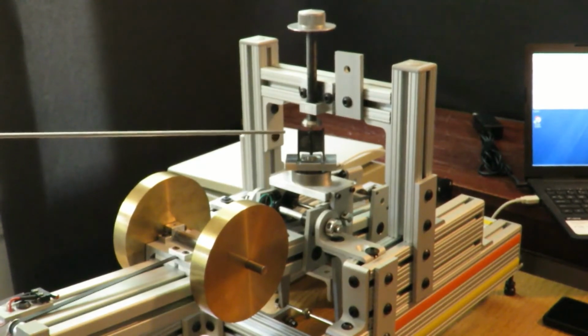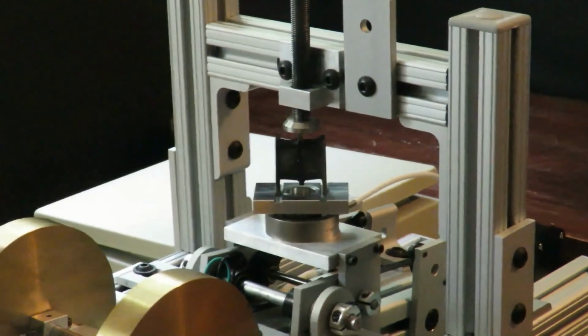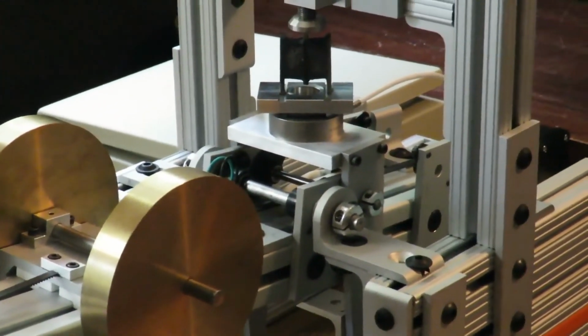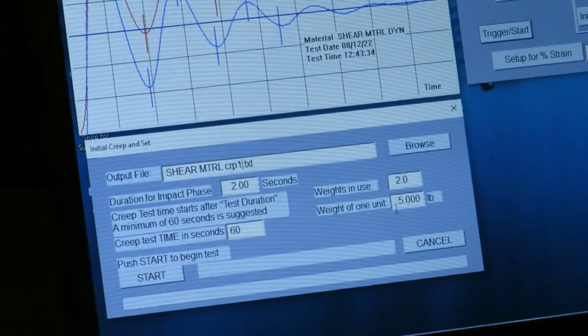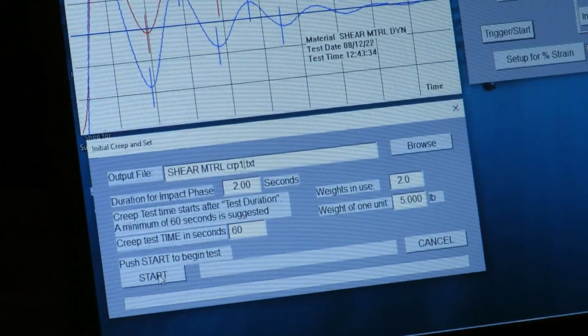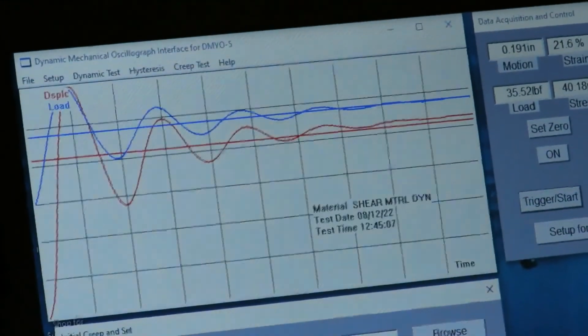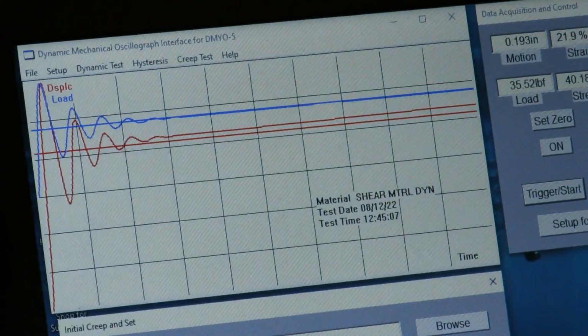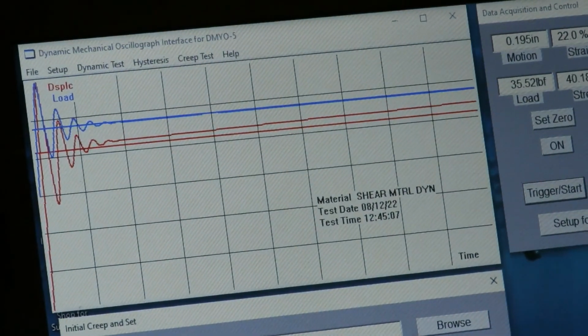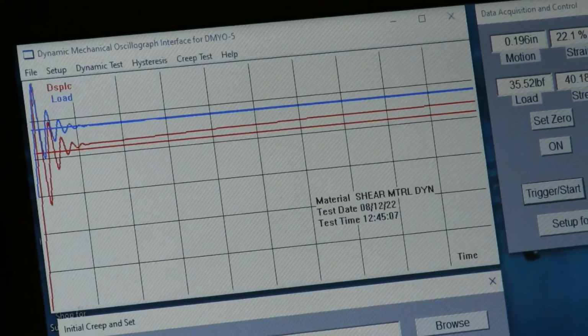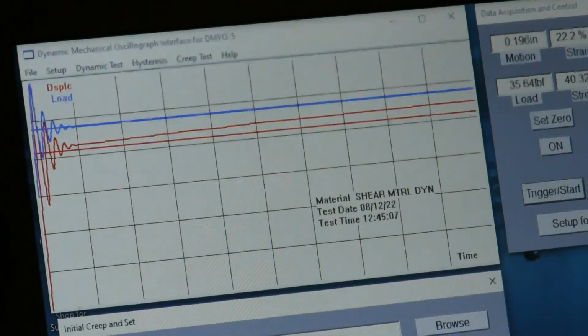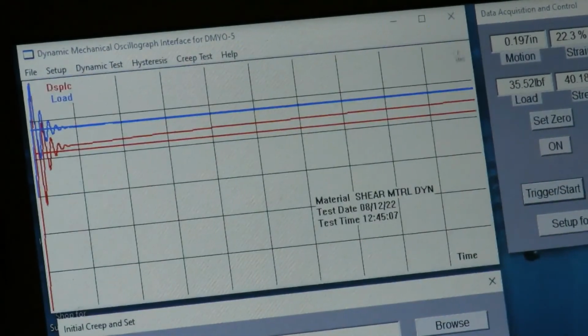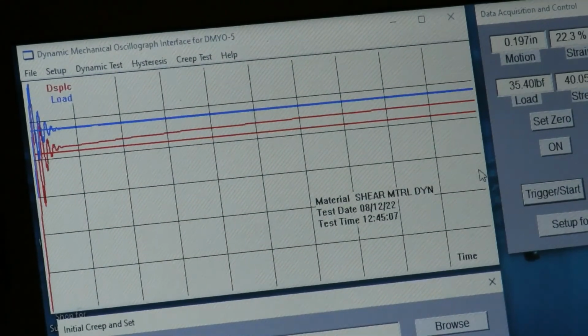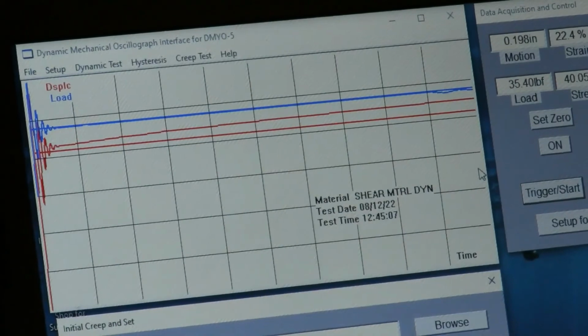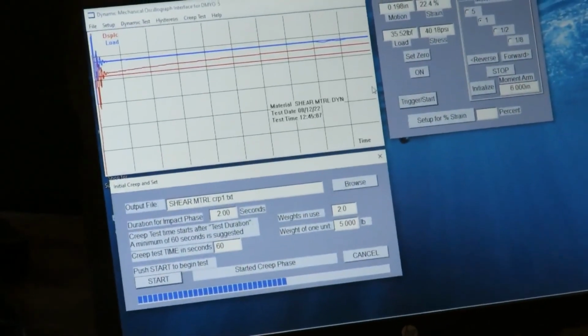We shall run a creep test on this shear specimen, same conditions as we did on the dynamic test, and we will allow 60 seconds for the creep test, and we are setting up, ready to go, and go. And once the creep starts, the plot collapses towards the left, and displacement shows if the creep is actually happening, which we can see a little bit here. As you can see, as the seconds move, the bar graph at the bottom shows the time function.